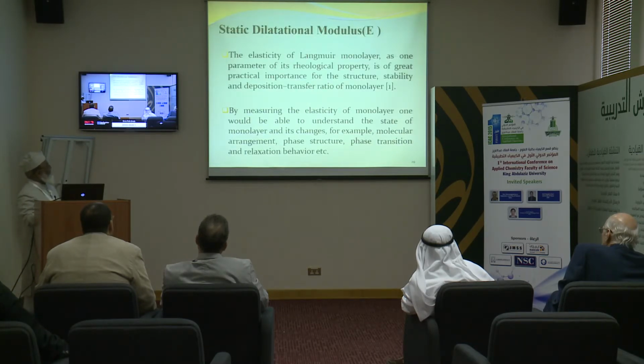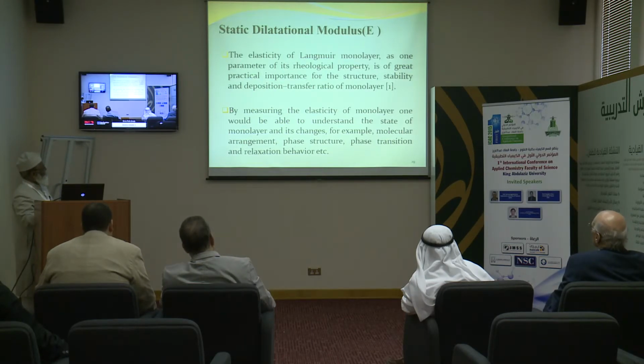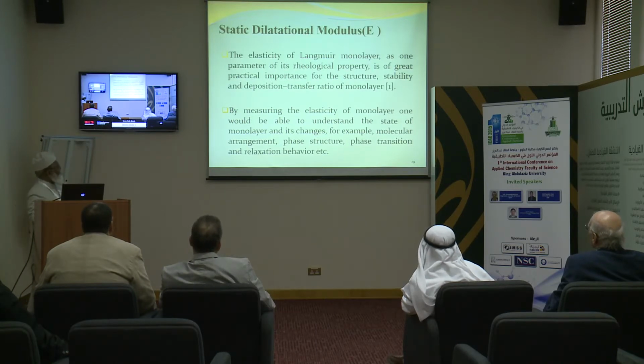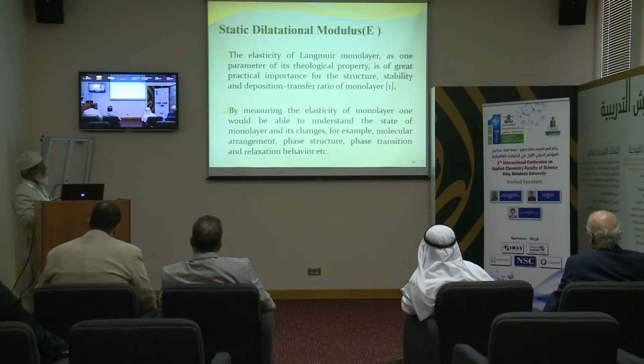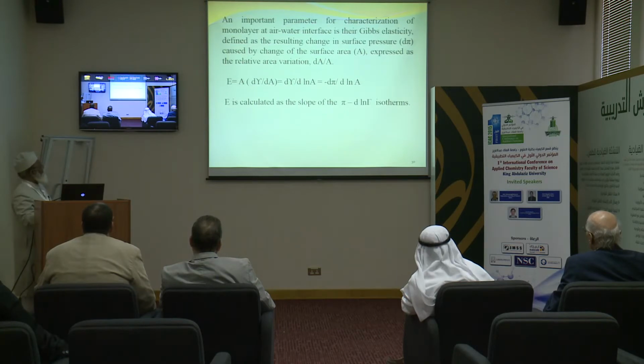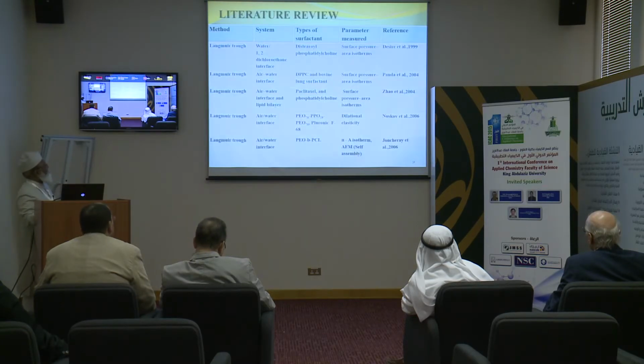Another parameter is the dilatational modulus. The elasticity of the Langmuir monolayer is one of the important parameters of its rheological property. By measuring the elasticity of the monolayer, one would be able to understand the state of the monolayer and also its changes, for example, molecular arrangement, phase structure, phase transition and relaxation behavior, and we can calculate it from the slope of the surface pressure versus area isotherms.